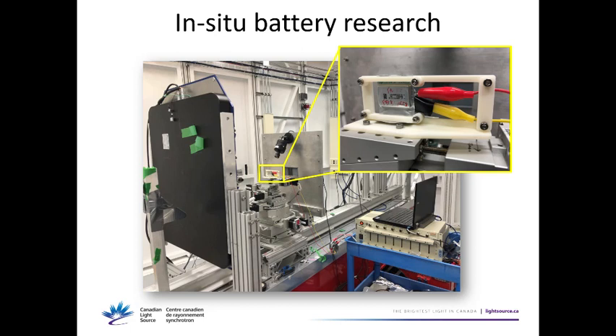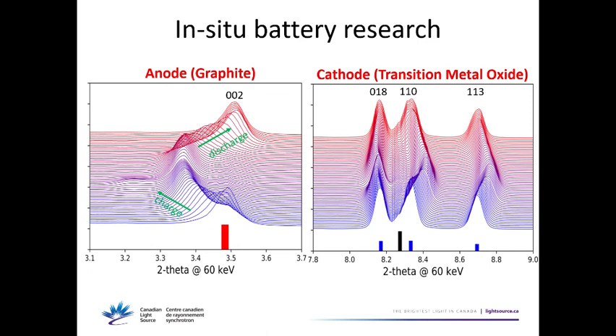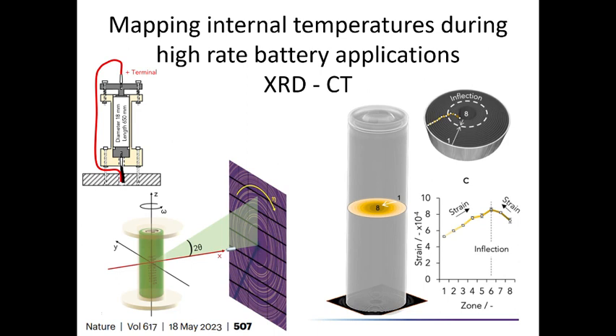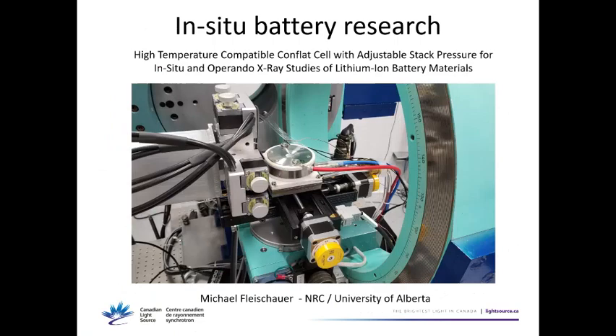We have many users doing battery experiments. High-energy X-rays go through real batteries so we can investigate how the anode and cathode are changing during cycling. We also do 3D mapping of the battery interior: using the lattice parameter from diffraction, we can extract strain and then temperature inside the battery — important because batteries heat up during operation and need to cycle many times.